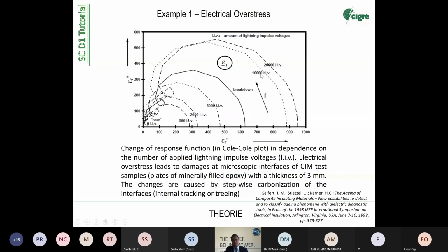And so these materials here may look pretty fine from outside, but inside they're already damaged. They're damaged by treeing, they're damaged by voids, partial discharges, carbonized areas. So should we work further with these materials? Also, they withstood so many lightning impulse voltages. For me, the answer is very clear. The answer is no, because these outer circles, these semicircles, are in reference much farther away than samples where we already had breakdowns. So you can see this is maybe a limit fingerprint where this material is end of life. It's just an academic example. It's not on real installation, just on small sample installation.